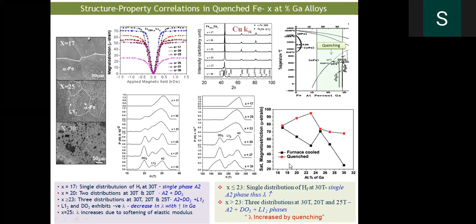But the same thing did not happen in furnace cool because it's more of an equilibrium process. In an equilibrium process, you also get the other phases coming into the picture. So this study has shown that by using iron gallium around a composition of 22 atom% of gallium, we can achieve high magnetostriction. This has been completed.